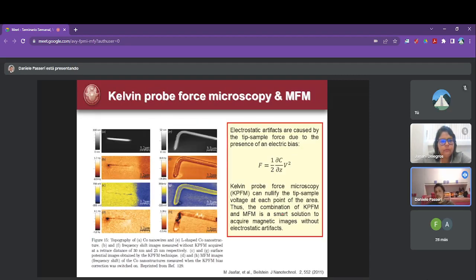So there was a very clever intuition by Professor Agustina Asenjo from the Spanish Council of Research. They said, when you have electrostatic artifacts, you have a force. The force depends on the tip sample voltage. But if some of you happen to work with atomic force microscopy, you can create a system to measure the tip sample voltage, which is the so-called Kelvin probe force microscopy.